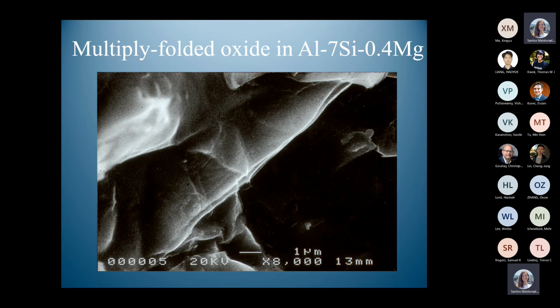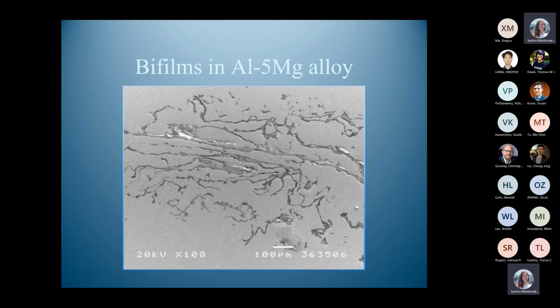And here are some of the things under the microscope. You can see this is multiply folded, and the tiny thing here is about 20 nanometers or something. And here's a situation where we've polished the surface, revealing this big tangle of bifilms. And here we've just taken off the top of the film, so that you can see the film underneath in places. So it really is a double film.